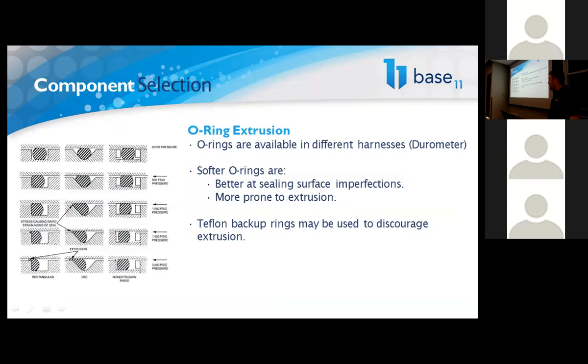but also soft enough that it's going to give you a proper seal with the kind of surface finish that you're working with. They've got something called backup rings that are available specifically to prevent extrusion. And so the column on the right-hand side of that figure shows what that looks like. Basically, they tend to be Teflon rings that fill in that gap and support the O-ring material as it gets squeezed over to that side of the groove to cut down on the chances of extrusion.